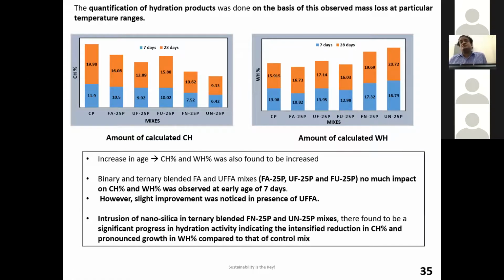Now, the equation I told you a couple of slides before, if you follow that equation, you can determine the amount of calcium hydroxide in your mix. Now you can see here 7 days and 28 days. As you know, in the beginning of your hydration process, definitely your calcium hydroxide will start forming, and at 28 days we are assuming that the hydration is almost over, or a significant percentage is over. Then I will say, for a control paste, it is the highest percentage of calcium hydroxide.